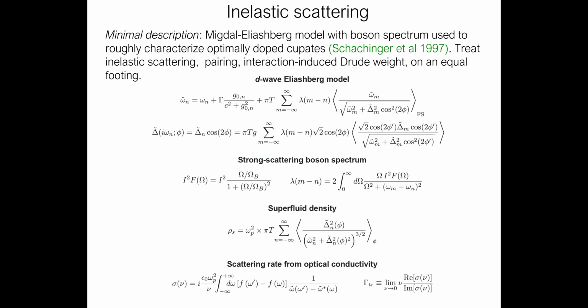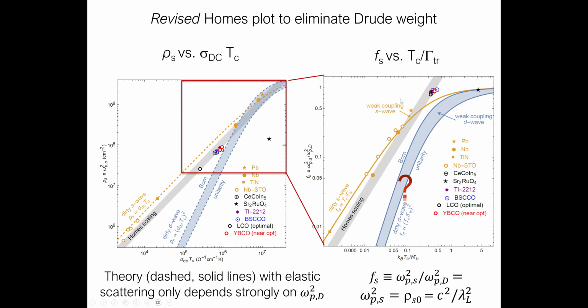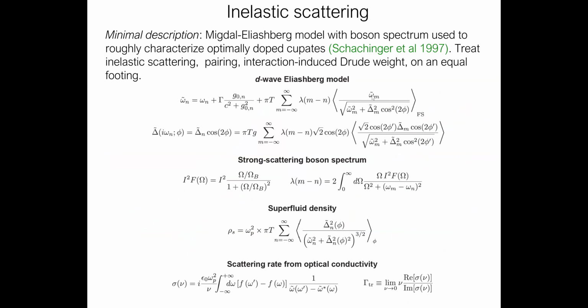Now let's remember that cuprates near optimal doping are dominated near Tc by inelastic scattering. There's some kind of bosonic scattering, call it spin fluctuation scattering if you want, which dominates the scattering rate. And so we thought, let's see what happens if we try to model this. We did the simplest possible thing to model the inelastic scattering and put it back into the theory. This is a model that goes back to Jules Carbotte and Erwin Schachinger. It's just the Eliashberg equations, which you probably recognize, for a D-wave superconductor. That's where the cosine 2 phi comes from. And some kind of ansatz for a strong scattering boson spectrum, which looks very generic.